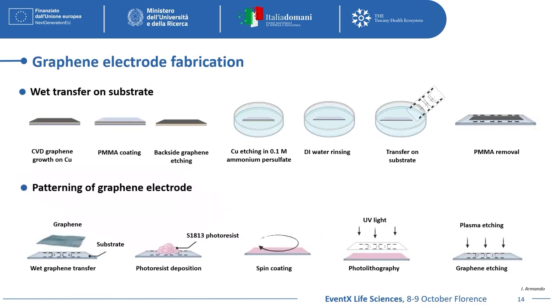Thanks to the combination of two different techniques, we obtain monolayer graphene on the glass substrate. Through chemical vapor deposition on a copper substrate, we obtain the monolayer, and then it is transferred to the glass by wet transfer. Once we obtain the monolayer of graphene, we are able to pattern it with traditional lithography, and we can obtain the design of the electrodes.